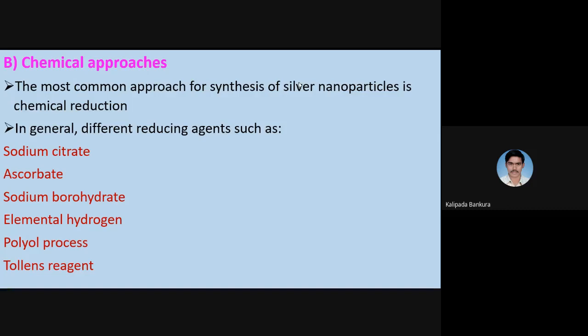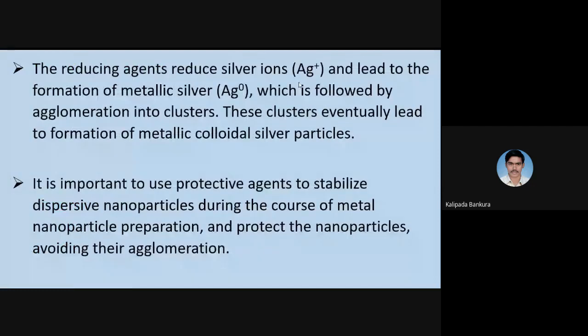In general, different reducing agents are used. They are sodium citrate, ascorbate, sodium borohydride, elemental hydrogen. The reducing agent reduces silver ion to silver metal, which is zero valent, followed by agglomeration into clusters. These clusters eventually lead to formation of metallic colloidal silver particles. It is important to use a protecting agent, that is a capping agent and or stabilizing agent, to stabilize dispersed nanoparticles during the course of metal nanoparticle preparation and protect the nanoparticles, avoiding their agglomeration.